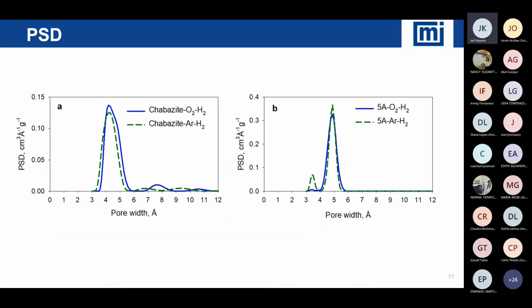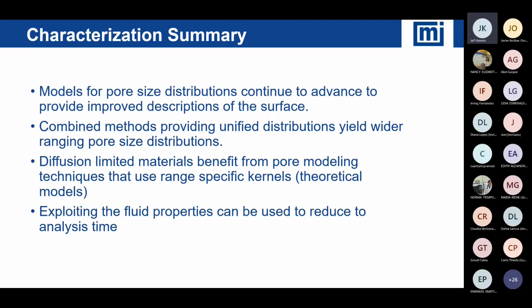Okay. When we calculate the pore size distributions with these different molecules, and again, we're using two simultaneously. We don't use a single gas anymore. We want to use two because we've established that technique gives us the highest resolution. We see that either hydrogen and oxygen or hydrogen and argon give us the best results, and we can get resolution down to 4 angstroms now. So very effective for looking at different materials and getting the highest possible resolution by combining things.